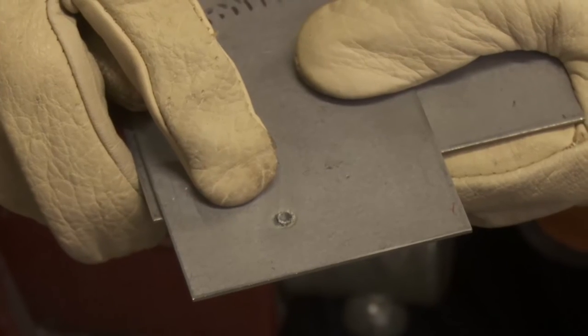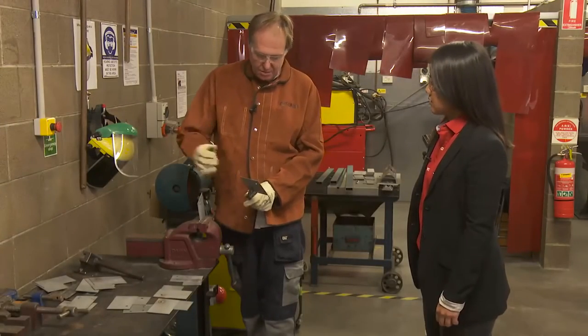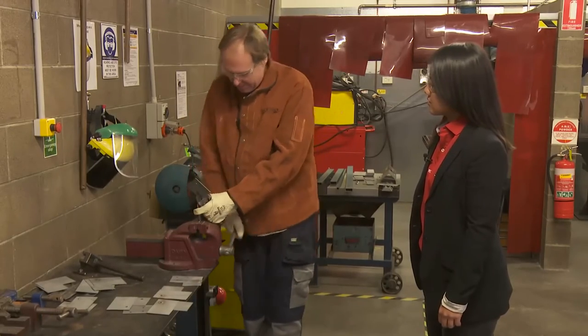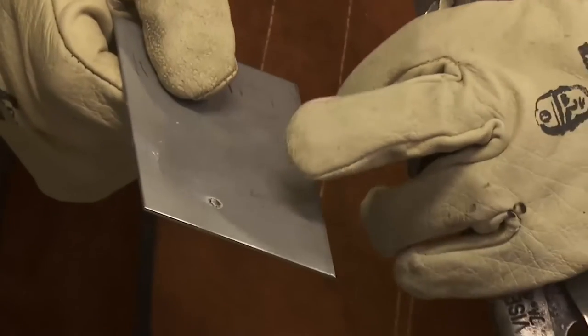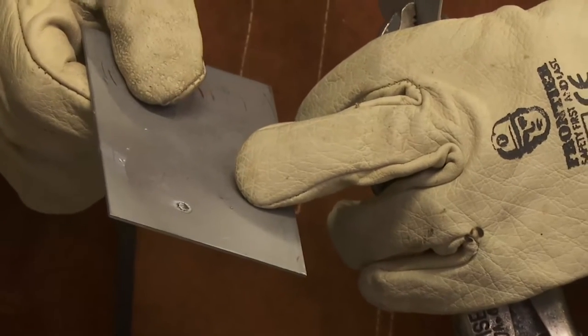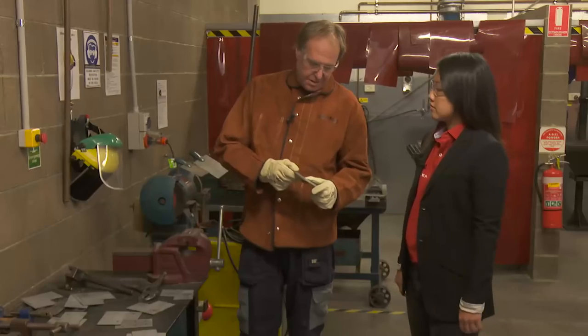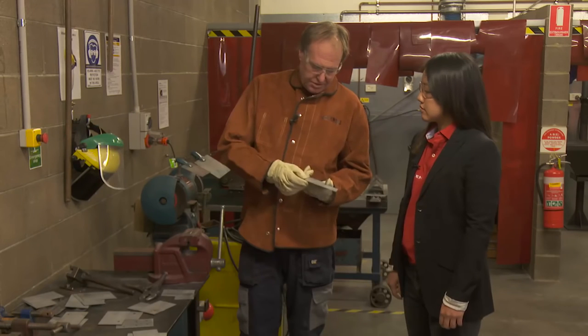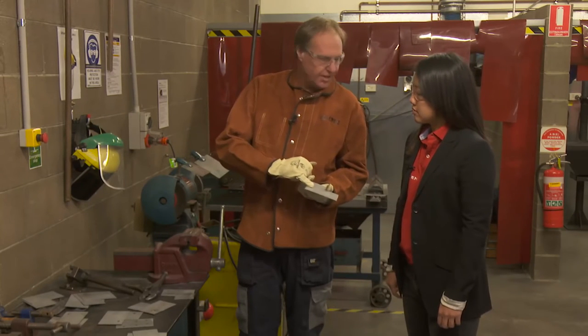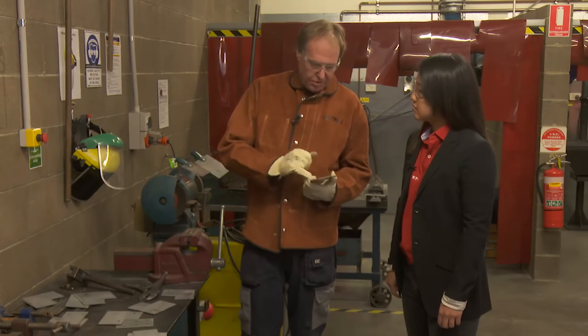The reasons for that, head size is too small. And the other thing this one doesn't have, if you look at the back of the base plate, shows only very little heat mark, no actual penetration. This is another plug weld that we've done. You'll see on the back of it, it has a raised area showing the penetration. We should get a good result out of this.